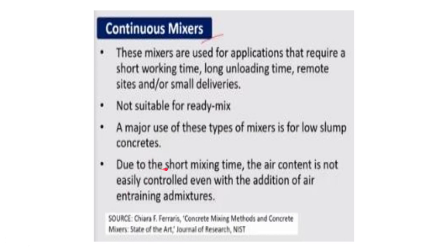Due to the short mixing time, the air content is not easily controlled even with the addition of air entraining admixtures. So this is one of the anomalies of continuous mixers. Because of the short mixing time, air content is not easily controlled, because of which the properties may vary even with the addition of air entraining admixture.